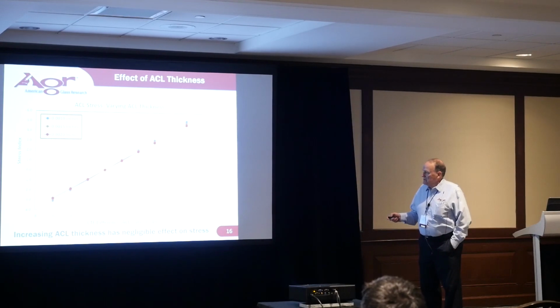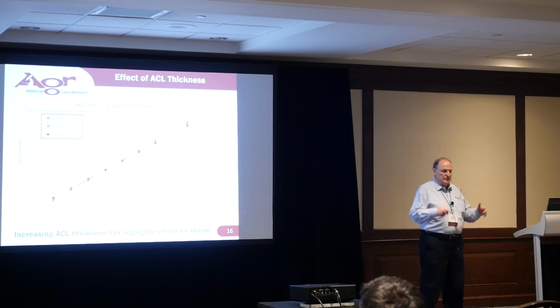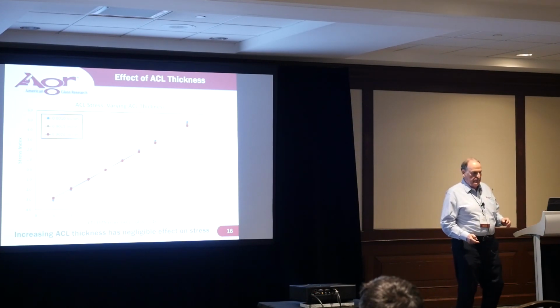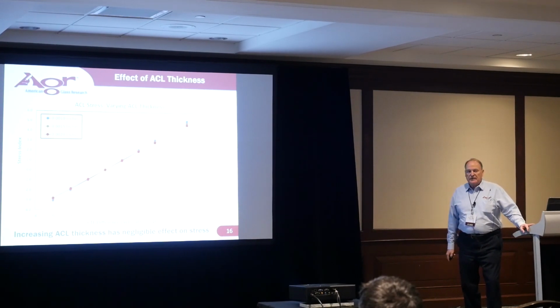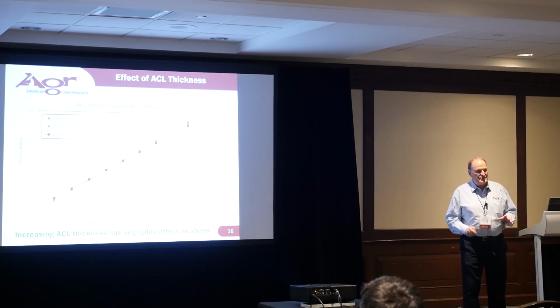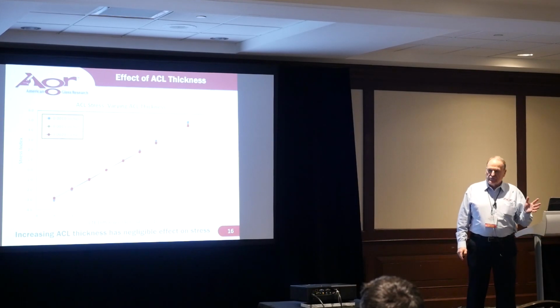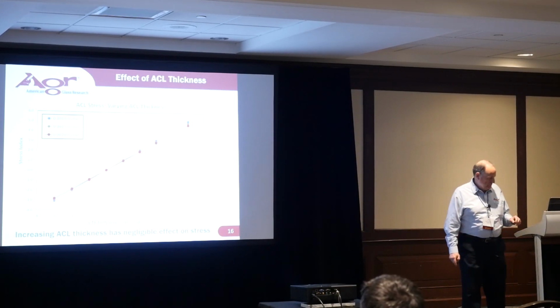What we saw also is that when the coefficient of expansion of the ACL was greater than the glass, we were creating tension stresses in the ACL. And when the coefficient of expansion of the ACL was less than the glass, we were generating compressive stresses in the ACL. What we expected. So, the effect of the ACL thickness, yes, there's a slight effect there, but overall, essentially negligible.